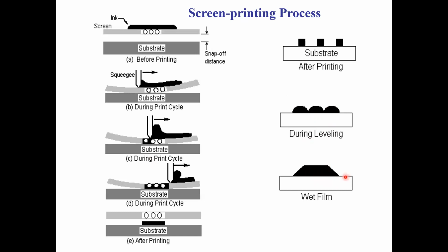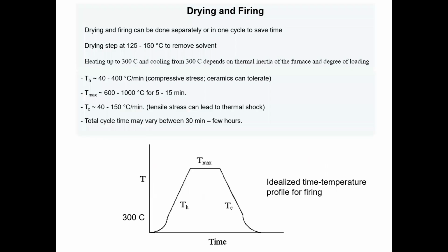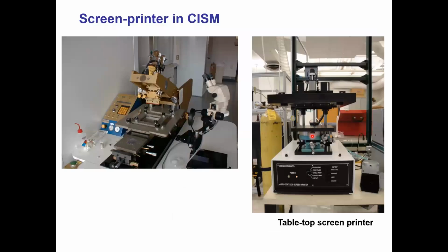And then we'll talk about how do you know what wet film thickness you have to print to get to the dried and fired film thickness that you desire. After we're done printing, then we usually go through a drying process and a firing process where we ramp up to a desired temperature. Typically for a lot of the oxide, you're talking about firing in the range of 600 to 1000 degrees Celsius. And you hold it there for some time and then cool it down. So again, this is an idealized kind of firing process of the film.